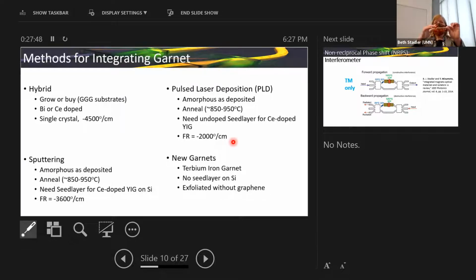So if you could just put down YIG and anneal it and be done, well, you'd pattern it, put down the YIG, rinse off your photoresist, anneal it, you'd be done, but you only get 200 degrees per centimeter. So you have to repattern all of it, put down the doped garnet, strip that resist off, anneal it again. It's just a lot of extra processing.